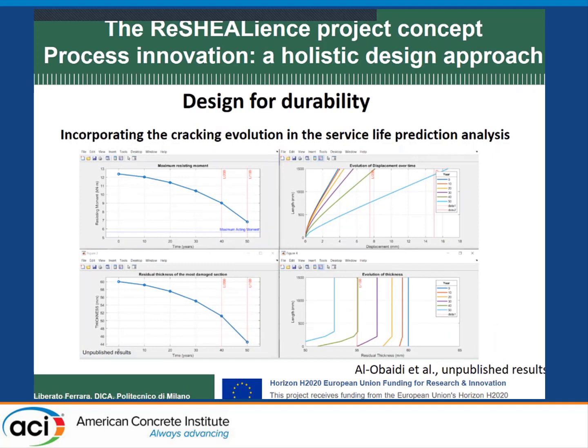I have a PhD student and a couple of master students working on this. We have the maximum resisting moment as it degrades over time, and the displacement up to 56 years. How do they evolve? You can see on the bottom right, starting from a 60 millimeter cross section, you progressively degrade, but the degradation is higher at the bottom because there you expect a higher crack and so a higher penetration of the aggressive agents.